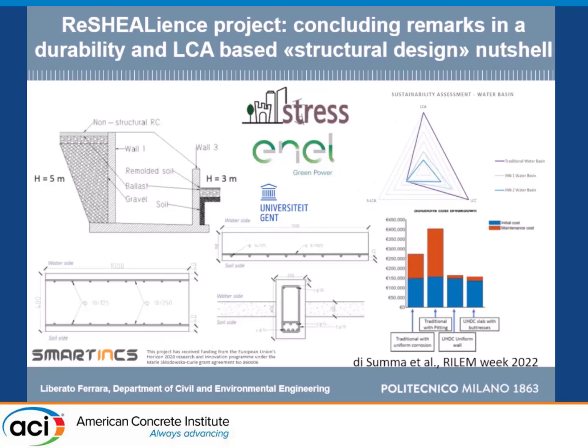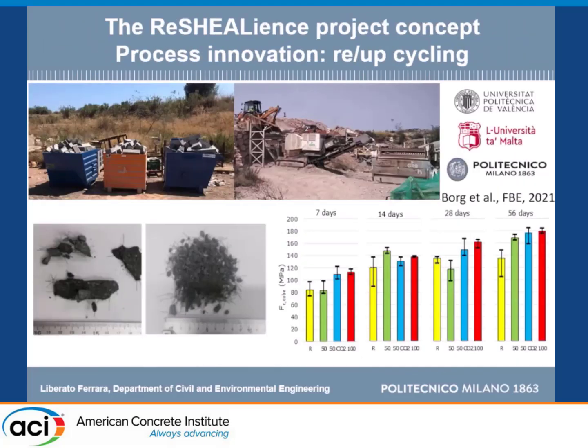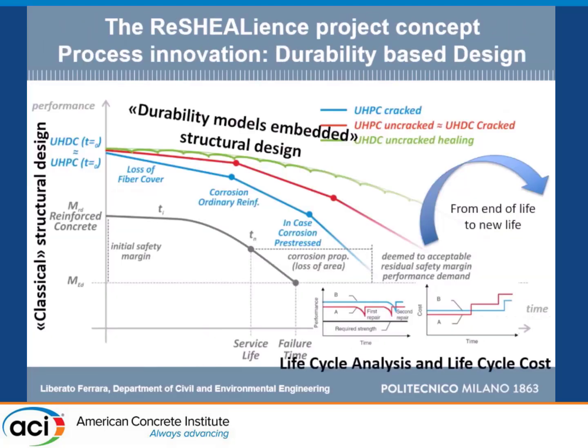For an ordinary structure, you go from 1,000 millimeter thick walls to 400 millimeter thick walls in the case of UHPC. Construction costs remain quite the same because of the reduction of the overall volume, but with ordinary concrete, you increase maintenance because of degradation and corrosion, and with UHPC, you use much less. What happens at the end? Because if you say that a structure lasts 100 years, probably your stakeholder will say, I don't need it. In 50 years, I will abandon the site and so on.